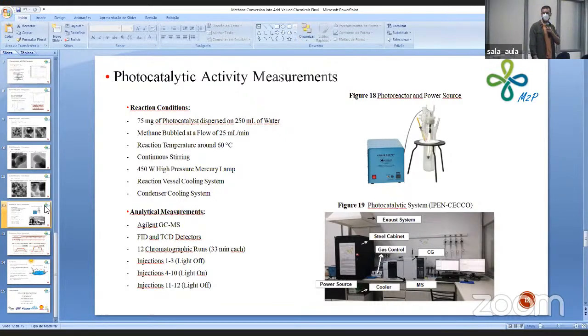As analytical measurements, we use mass spectrometry in order to identify the formed products, and gas chromatography so we can quantify the formed products. An FID detector was used to quantify most of the products, and a TCD so we can see if we have some hydrogen formation during the tests. We have a total of 12 injections of 33 minutes each, in a total of seven hours of photoactivity measurements. In the first 2 injections, the light was off. At injections 3 to 10, the light was on. And at the last 2 injections, the light was turned off again in order to see the influence of light in our system.